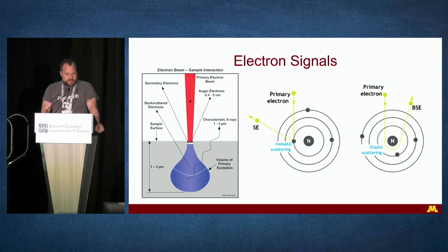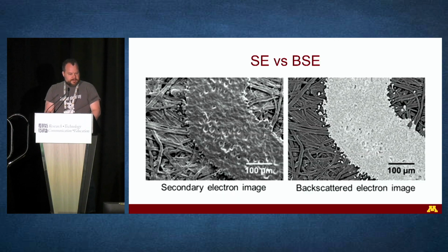So here's just a quick example of what secondary and backscattered electrons are. The secondary electron is an orbital electron that's been ejected from the material. The backscattered electron is a beam electron that's been bent around the nucleus and comes out. There's an energy difference between them, and that's how we detect them. As a quick example there, the secondary electron image on the left shows us nicely the topography. This is actually just the corner of a letter printed on a piece of paper with a standard inkjet printer. You can see all the lumps in the printing, you can see the fibers in the paper, but then in the backscattered image, the printed ink is much, much brighter, denoting that it's made of heavier atomic number elements, and so we get a compositional contrast image. And the combination of the two images really tells us an awful lot about the material.